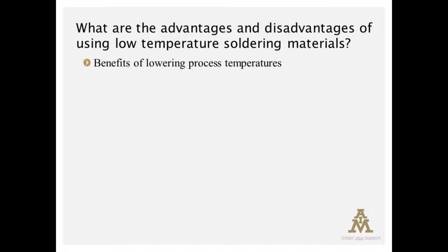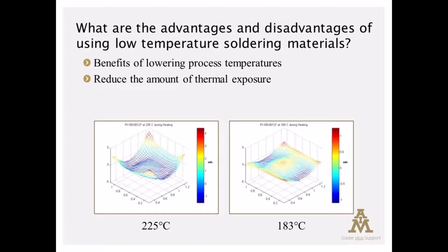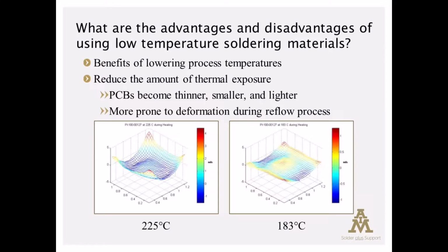So by lowering the process temperatures, we can reduce the amount of thermal exposure of the assembly, which has some significant advantages. The most significant, and it correlates with what's happening with the electronics assembly market in general, is that as circuit boards become thinner, smaller, lighter, and more capable, they are more prone to deformation during the reflow process. So a very thin substrate and a very thin component, when exposed to SAC 305 soldering temperatures, will tend to deform or warp, which leads to soldering defects. So that's the main driver for the exploration into low temperature materials or reduced reflow soldering materials.